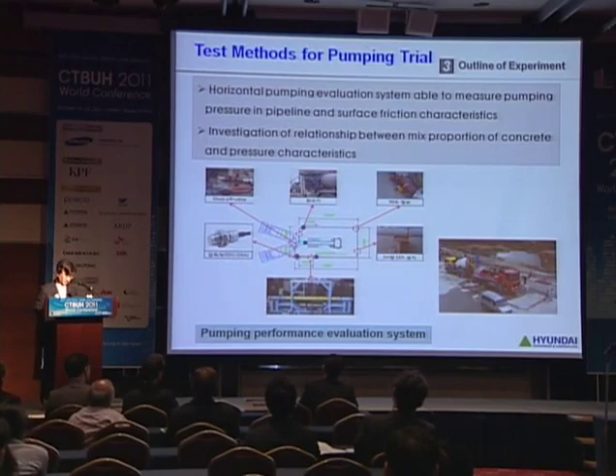Next, test methods for pumping trial. The pumping performance evaluation system, as shown in this figure, was developed to measure pumping pressure in the pipeline and inner surface friction resistance. Using this system, pumping characteristics with mixed condition and pumping condition of concrete were investigated. The length of the pipeline was about 50 meters. This is the pumping evaluation system, and this part is the testing pipe.